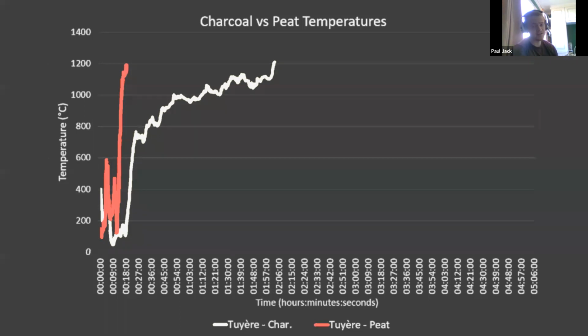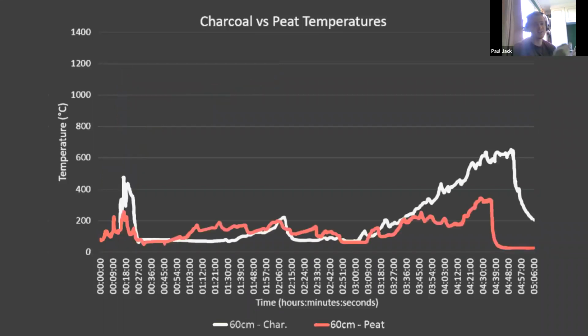And we can see that red, denoting the temperatures from the peat charcoal, it gets up to 1200 degrees almost 2 hours before the wood charcoal does the same. Unfortunately, we can't track the temperature beyond 1200 because the thermocouples we were using would degrade past that temperature. But nevertheless, we can see a really powerful thermal performance from the peat charcoal compared to the wood charcoal. If we look further up the furnace and actually look at the highest readings we took at 60 centimeters, they're basically the same.